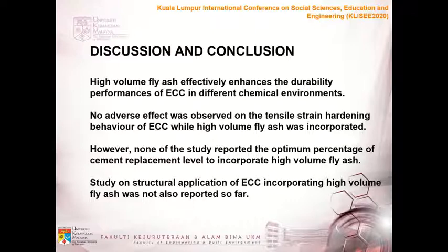Coming to the end, as conclusion, high volume fly ash effectively enhances the durability performance of ECC in different chemical environments like chloride environments, alkaline environments, then against freezing and thawing, and also water absorption. It was reported that there is no adverse effect on the tensile strain hardening behavior of ECC while high volume fly ash was incorporated. However, none of the studies reported the optimum percentage of cement replacement level to incorporate high volume fly ash.